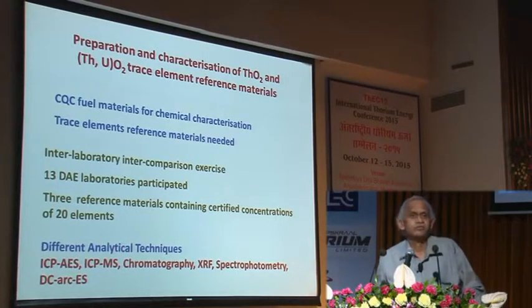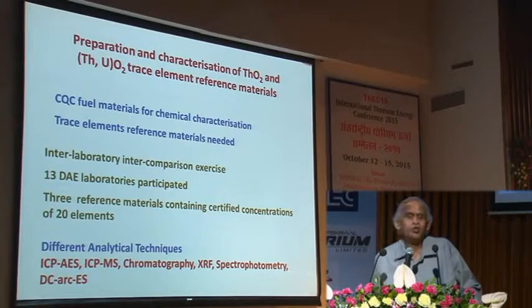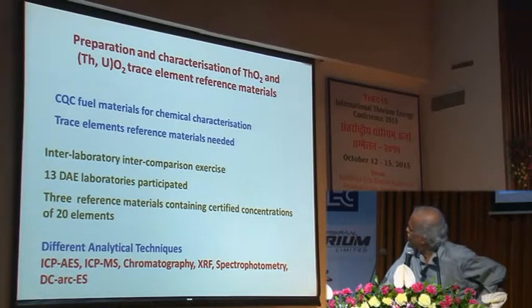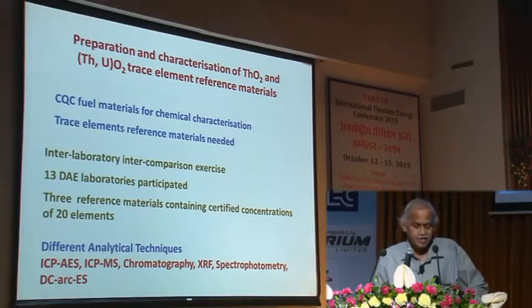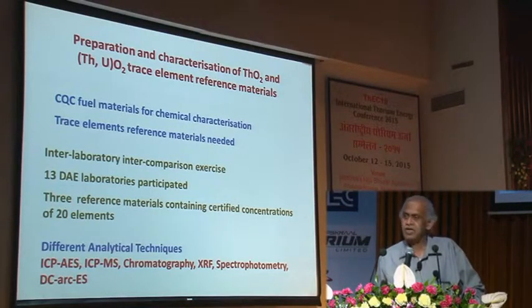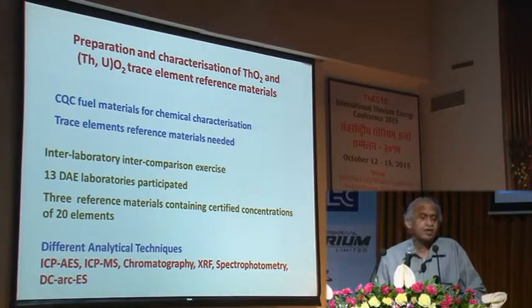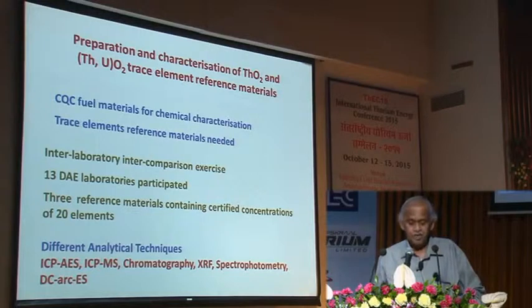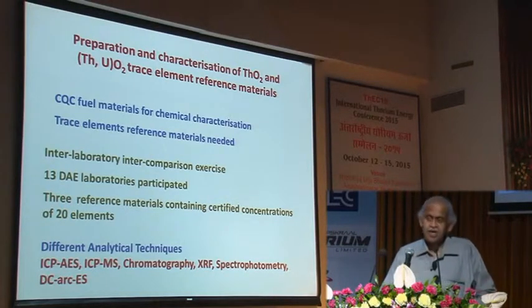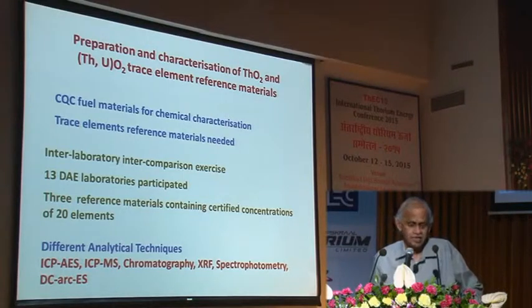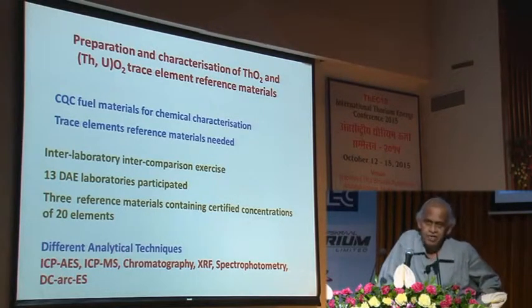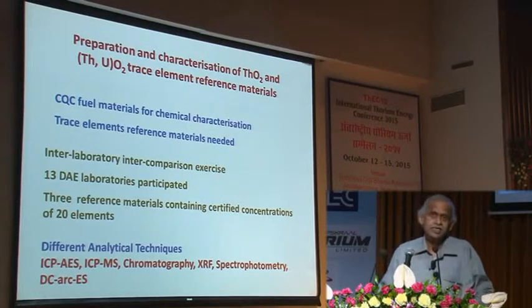So the first and foremost thing we require is the availability of reference materials for the chemical characterisation. In this direction, this group long ago did prepare copious amounts of thorium oxide and thorium uranium oxide reference materials with known impurity contents added, and these have been certified through a round-robin inter-laboratory intercomparison exercise, wherein 13 DAE laboratories participated, and 3 such reference materials have been prepared and certified for 20 elements. And in order to achieve this goal, different analytical techniques have been employed, and a rigorous statistical treatment has been applied before giving the certificate of these trace constituents present in these 3 so-called reference materials.